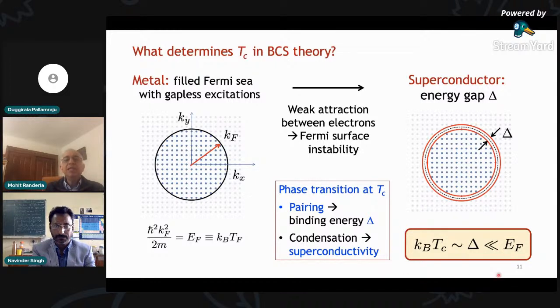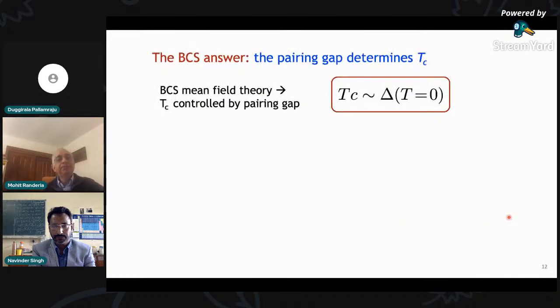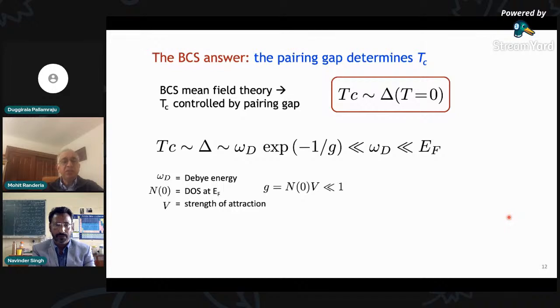And both of these scales are tiny, exponentially small compared to epsilon Fermi. In typical superconductors, TC is of order Kelvin, 10 Kelvin, okay? Whereas the Fermi energy is of order volts or 10 volts. And as you know, that's a huge difference of temperature scales. So in the BCS theory, the answer is TC is controlled by the pairing gap. The more strongly bound the electrons in a Cooper pair, the higher the transition temperature.